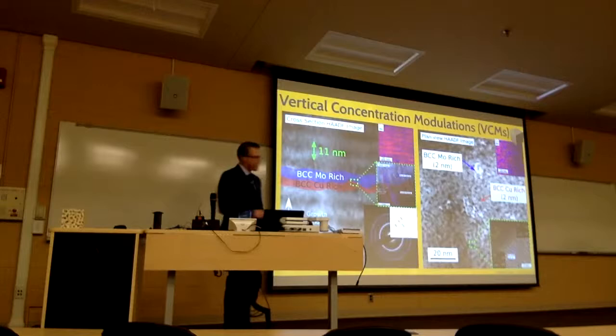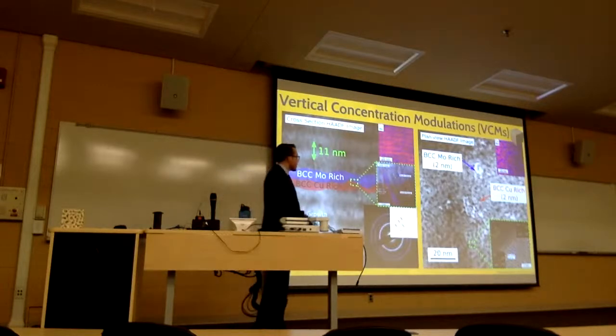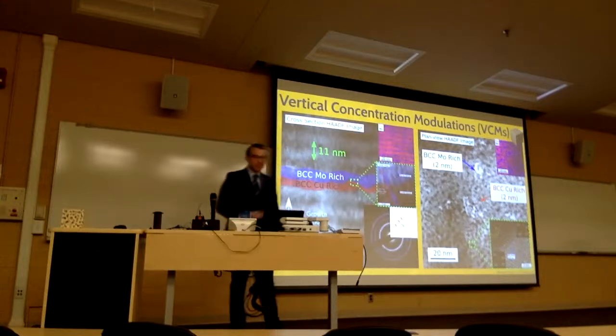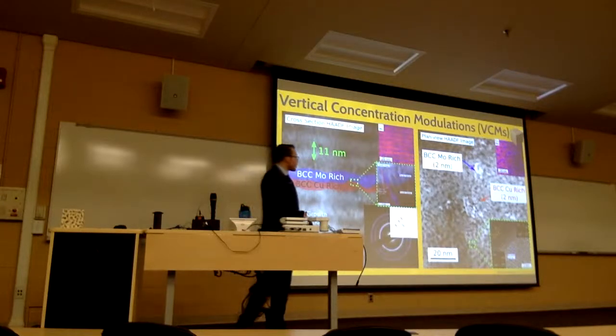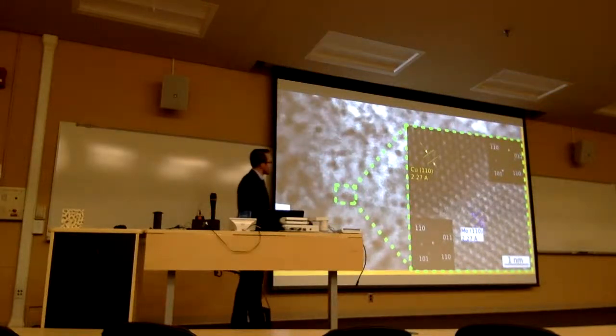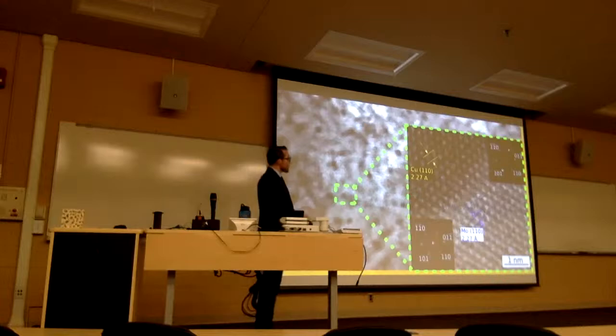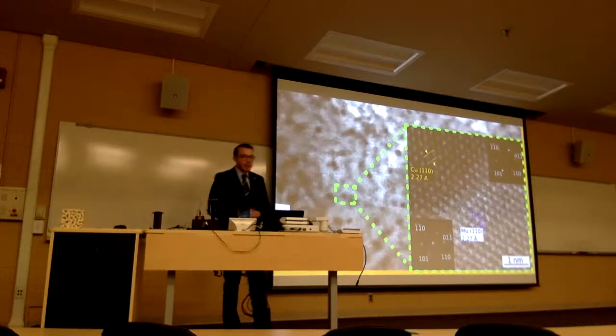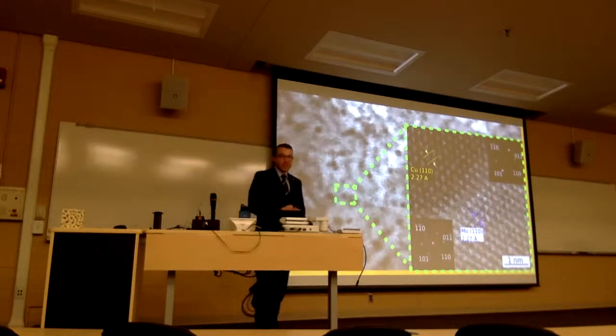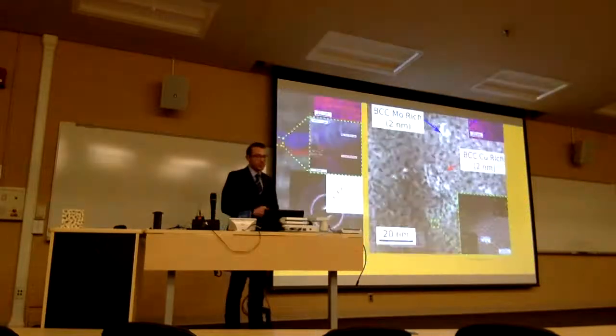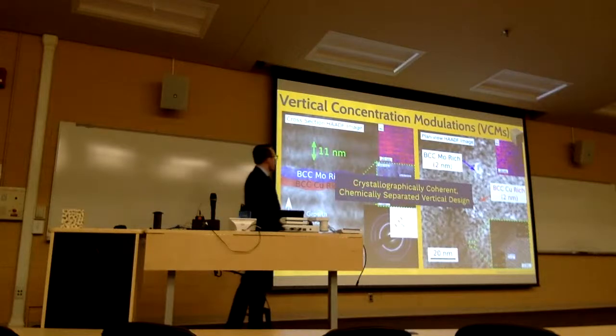And I'll show you that in detail in just a second. In plan view, when we look at the sample from top down, you can see these tortuous-like morphology into the thickness of the film with copper and moly-rich domains. And if we actually look at the interface between those two crystals in high resolution, you can see that copper is actually strained to match the lattice parameter of moly into a BCC crystal structure, forming a coherent interface between the two crystals. So in summary, what we have is a crystallographically coherent, chemically separated vertical design of the material.